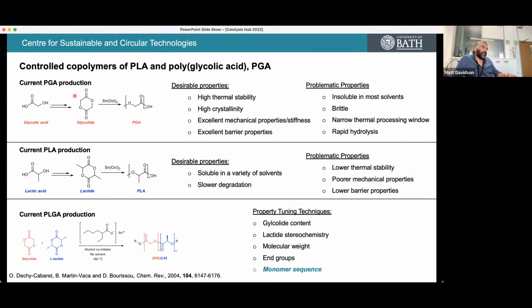It's the same polymer without a methyl group here on the monomer, and it's the same ring opening mechanism to make high molecular weight polymer. It's only more recently, actually, than PLA that high molecular weight polyglycolic acid has been available commercially. It's used in some very specific applications at the moment. There's lots of problems with it.